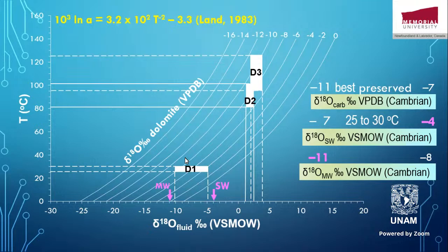However, for D1, we don't have a homogenization temperature from the fluids, simply because D1 was formed, its dolomicrite definitely was formed, at near-surface temperature conditions, and it's impossible to have two-phase fluid inclusions there. If there were fluid inclusions, they would probably be all-liquid inclusions, but the crystal size does not allow us to pick inclusions and measure them. So assuming that they were formed probably at temperatures between say 25 and 30, and this is an assumption, the delta O18 for the parent diagenetic fluid is between -5 and -10.